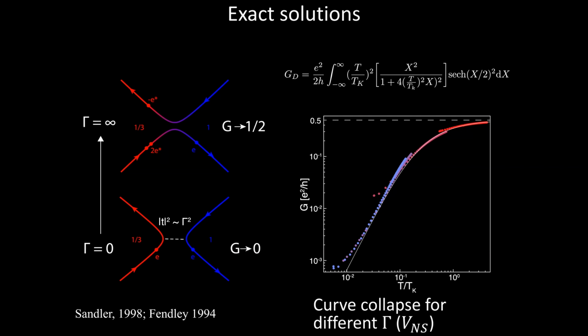At low biases, you are in this universal regime where you basically have low conductance. But what you can try to do is paste together this nu equals a third edge state with this nu equals 1 edge state by making the barrier between them extremely shallow. It's still true that at arbitrarily low energies you won't be able to tunnel, but it turns out there is another unstable fixed point in the RG language where something else happens. And in particular, there's a really unusual process that dominates this fixed point.